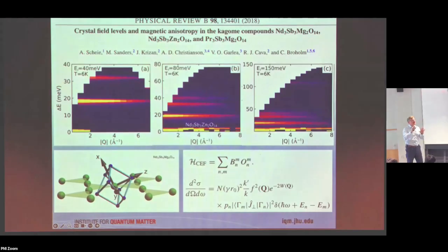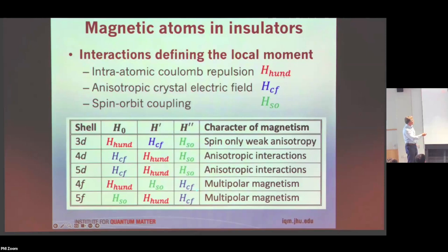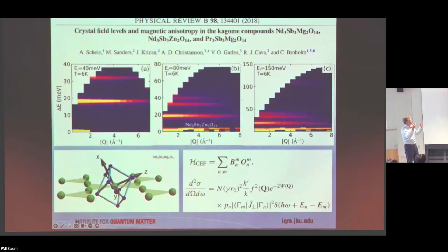So we're going to go to this part of our diagram. In this part of the diagram, it's really important to understand the nature of your low energy multiplet, so you actually need to know what the effects of this crystal field interaction are. I just wanted to indicate to people that neutron scattering is really a wonderful technique to figure out the nature of the low-lying multiplet. And there's a very, very easy experiment: the powder sample, you throw it on the machine, and in a couple of hours, you'll have the spectrum.